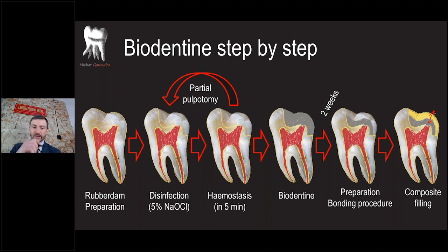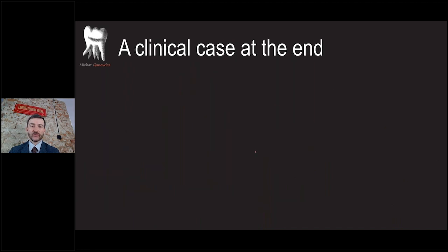To summarize, one of the most important things that you have to remember in this procedure, to have more than 90% success rate, is this: you have to reach hemostasis within a maximum of 5 minutes. If you are not able to reach hemostasis during the 5 minutes, remember of course about the disinfection. If you are still not able to reach it, you have to try to make a partial pulpotomy or full pulpotomy. But if it still doesn't work, you have to do the standard endodontic treatment, the root canal treatment. This is I think the most important thing that you have to remember.